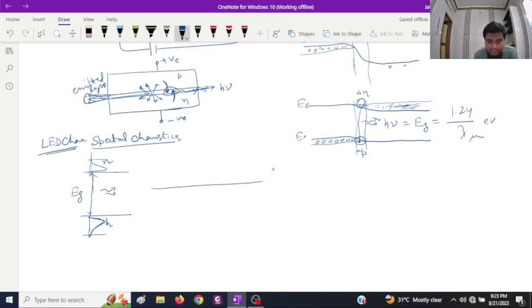So if you go for very large energy, or in terms of lambda, if you go for very small wavelengths, of course the emission will be zero, and it will go maximum up to the band gap, that is lambda c is equal to 1.24 divided by Eg. So after this it will be 0. So generally the characteristics are like this, and this wavelength spread, delta lambda, varies around 80 to 90 nanometers. The maximum, lambda max, corresponds to an energy slightly more than the band gap energy, and hence lambda max will be slightly less than lambda c.